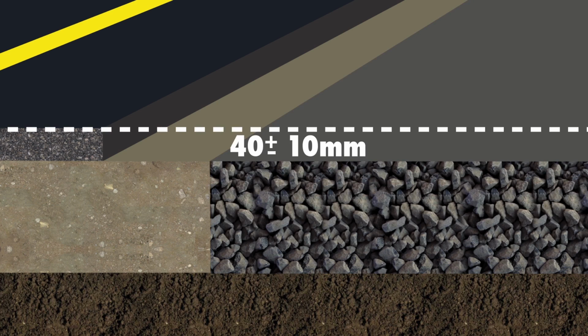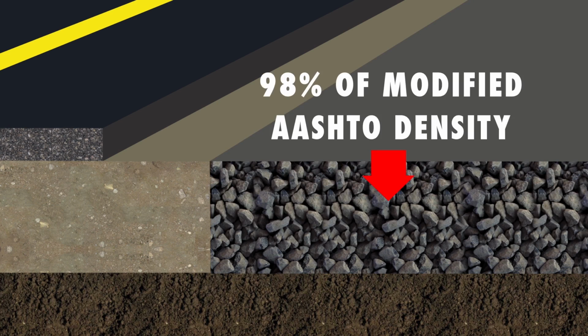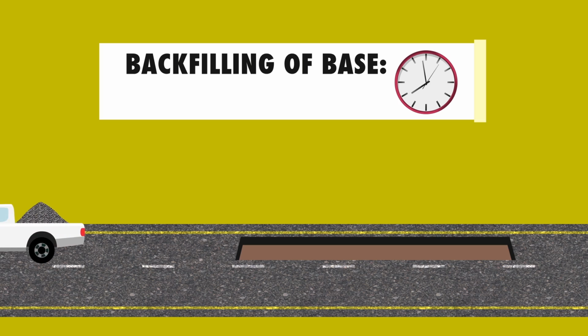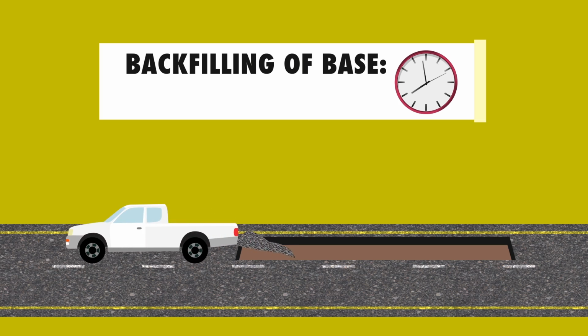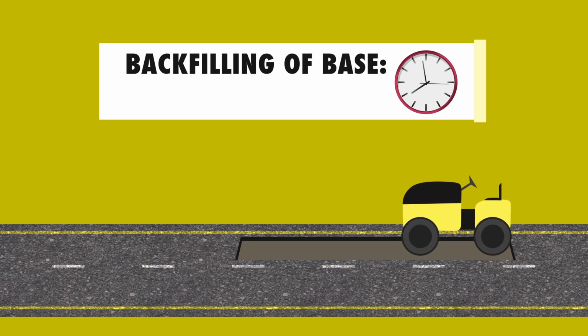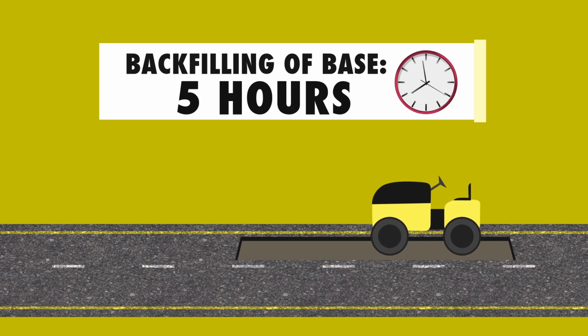the surface of the road. The density of the backfilling of the base layer should be at least 98% of modified AASHTO density. This whole process of transporting, backfilling, and compacting the base material should not exceed 5 hours.